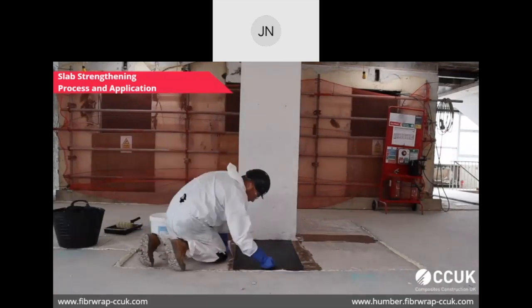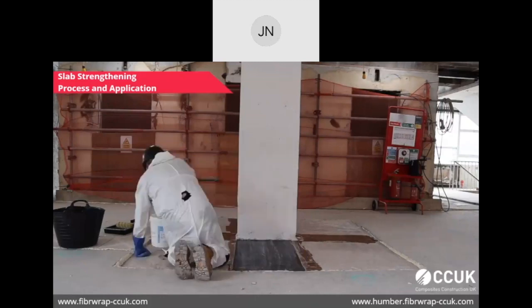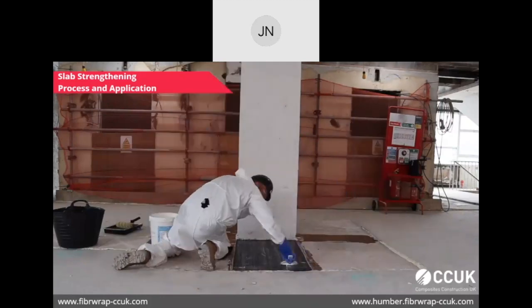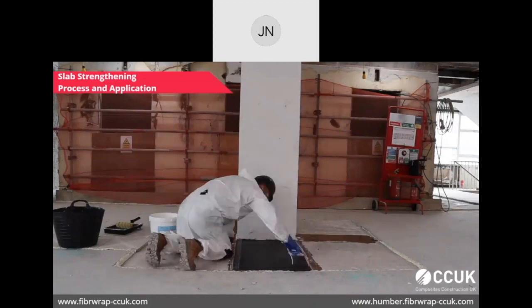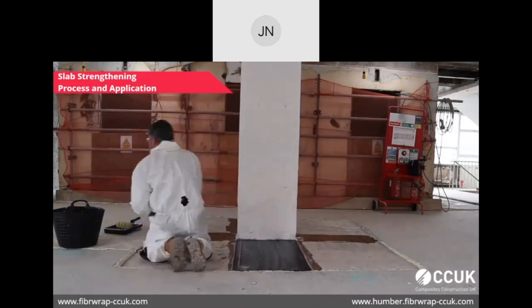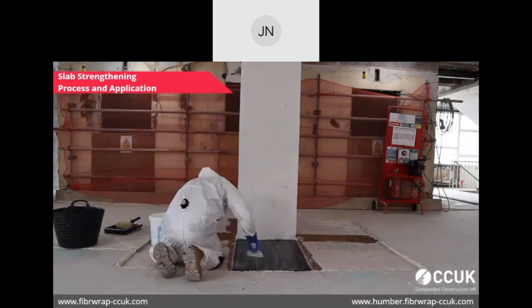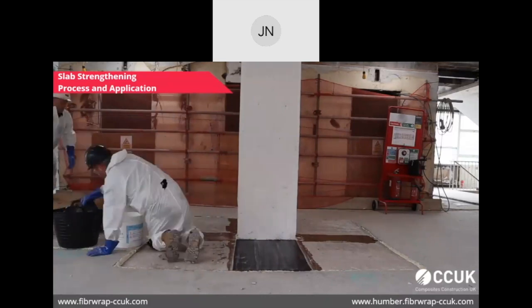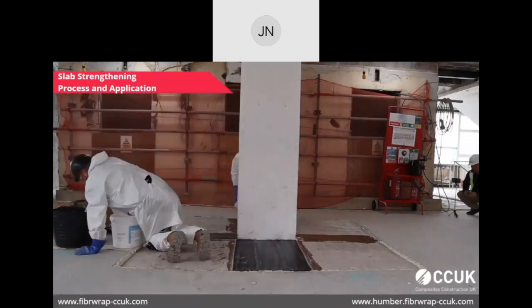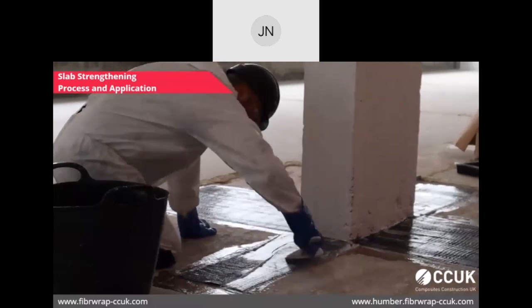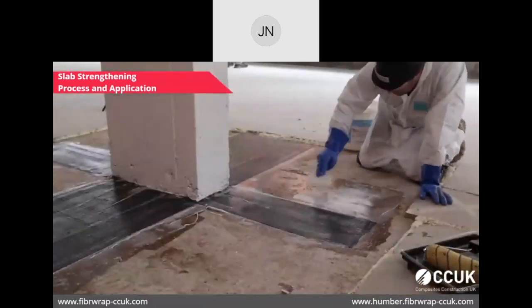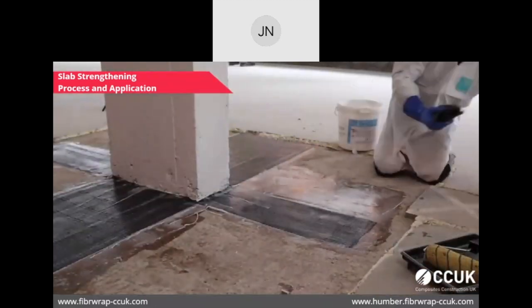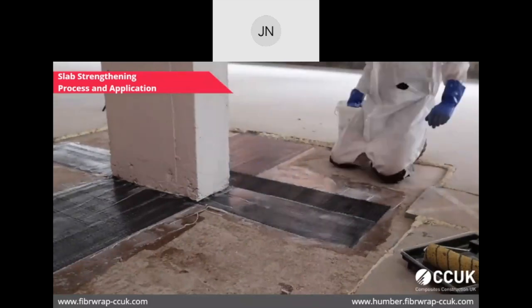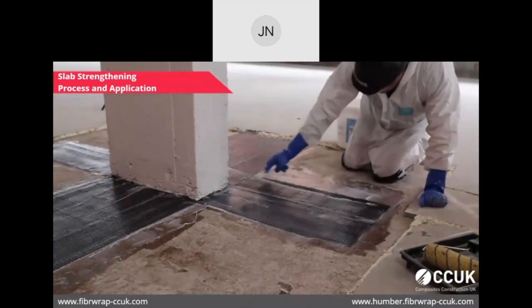Now the white colored stuff you're seeing is the thickened type of epoxy. That is thickened using silica fumes, and that is used so that the bond between the different layers of FRP and FRP to concrete can be increased. So once you've put the first coat of thickened epoxy, you put the first layer of carbon fiber, which is, as I said, saturated. So you saturate it before applying it. So the roll you are seeing, they are all wet fabric.